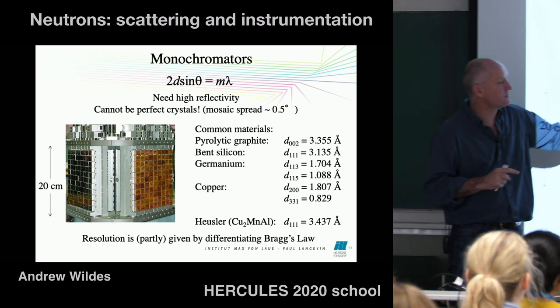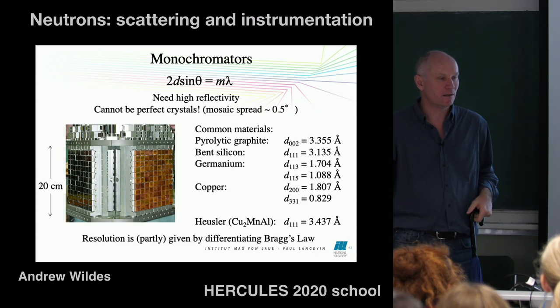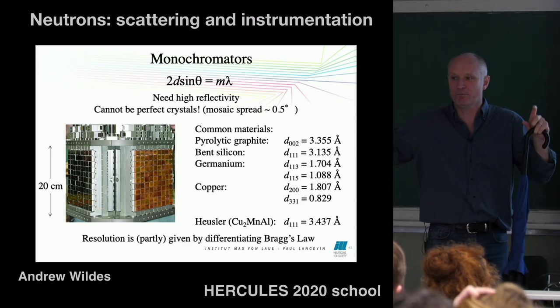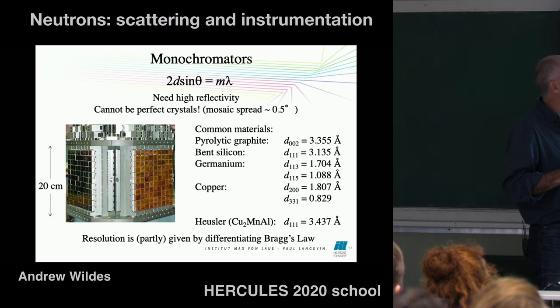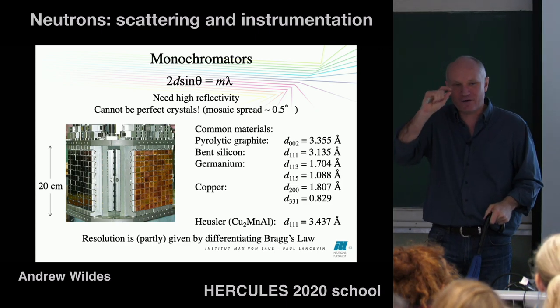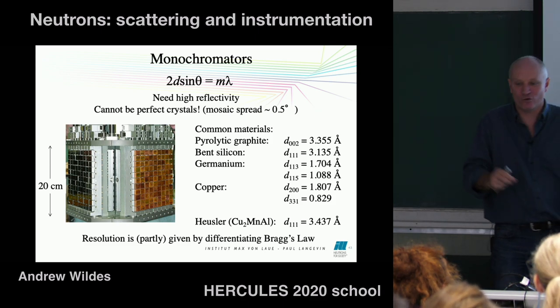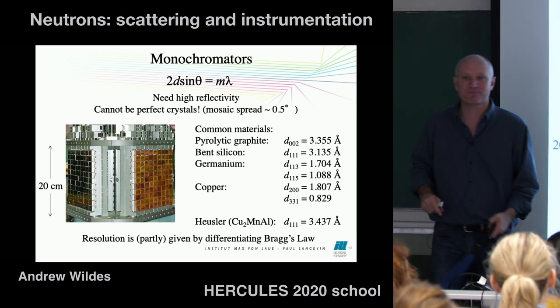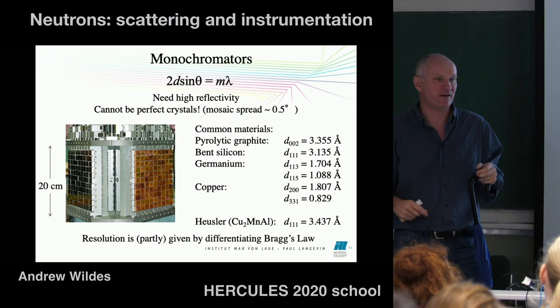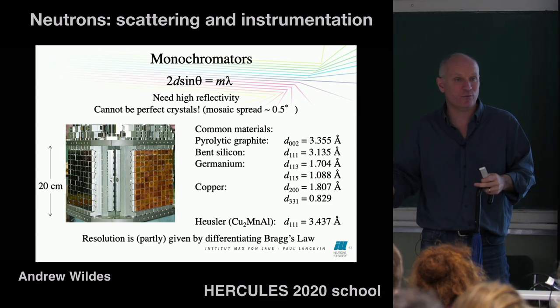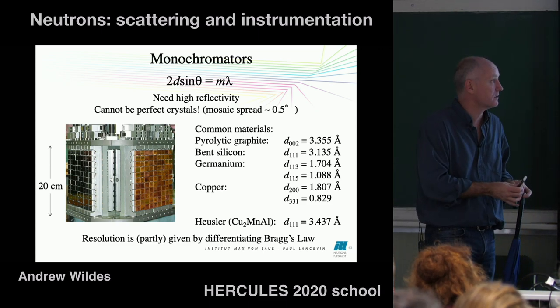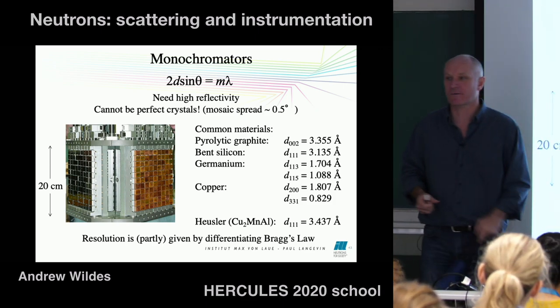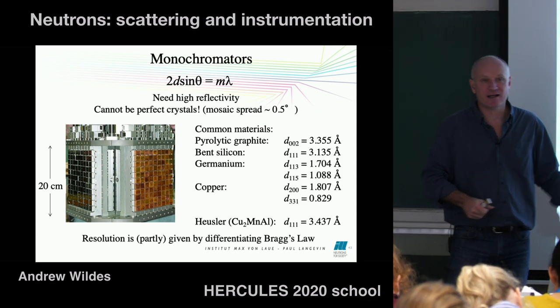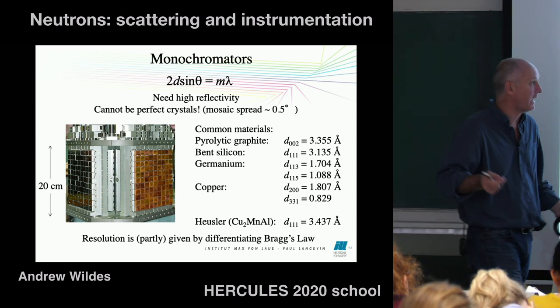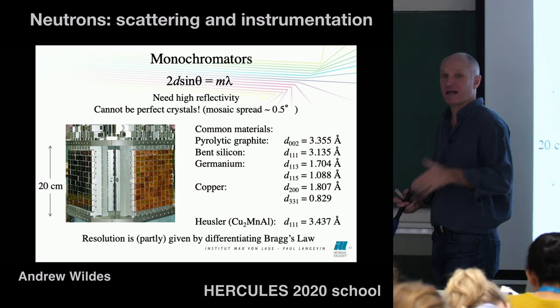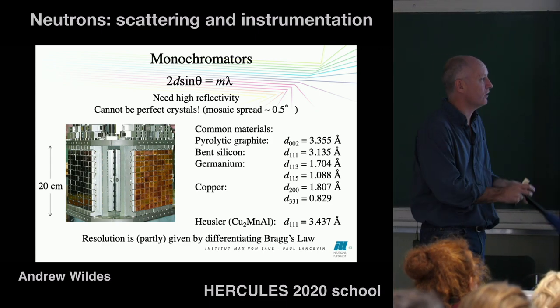Another thing that's very important, though, is it has an intrinsic mosaic spread, so it's not perfect. And this is very important for neutrons. If you get a crystal that's too perfect, then you constrain Bragg's law too much. You can only see either a very, very small delta lambda coming out, or you've got a very, very small delta theta that you can use. And that really limits the number of neutrons that you'll eventually get out of your beam. So because we have so few of them to begin with, we have to relax some of the resolution to get enough flux. And one of the ways we do that is to have non-perfect crystals with a mosaic spread that's a little bit larger. And graphite comes with an intrinsic mosaic spread. The best graphite you can buy commercially has about this mosaic spread. So it has a high reflectivity, very nice crystal properties. We use that a lot.